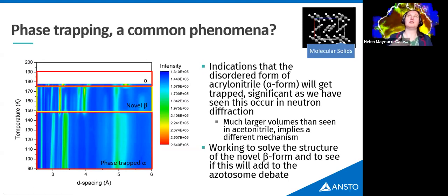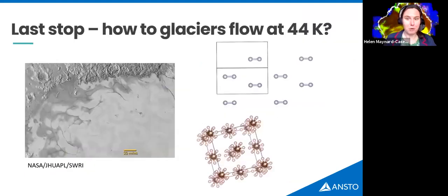So with the acetonitrile, we hypothesized that the phase trapping was happening because of strain from these really tiny capillaries. The capillaries we use for that are only 0.3 millimeters. In this sense, this is a disordered thing, whereas acetonitrile is not disordered, and it's also happening on a bigger sample. So the mechanism of this phase trapping is very different. So that's something that we've definitely got to delve into a bit more.